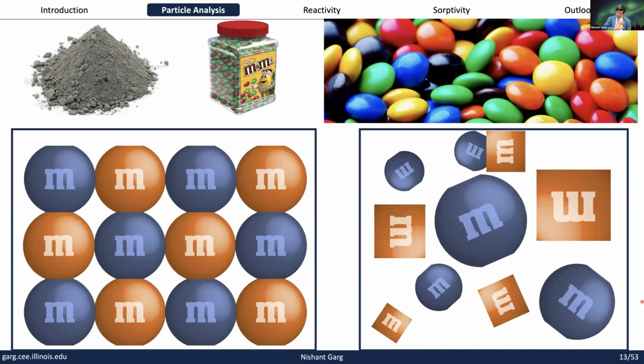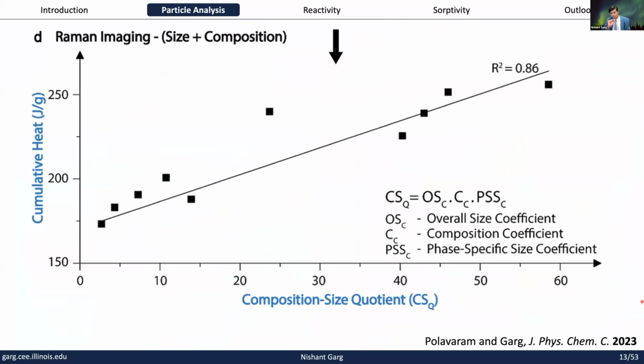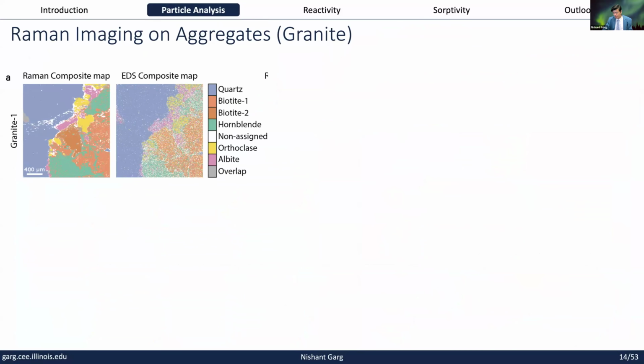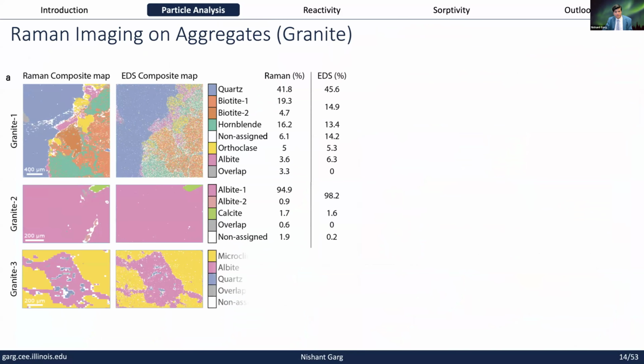So you can imagine all the cement particles are equal in size and shape and nicely organized, or they are randomly distributed. In the case of cements, it's really towards the latter, where what we then did is we took the individual particle size distribution of each cementitious phase, combined that with the amount, and came up with this very empirical parameter called the composition size quotient, which we can see is able to predict the 3-day cumulative heat of the cement paste made from these dozen different cements, which means that there is something about considering these individual phase size distributions.